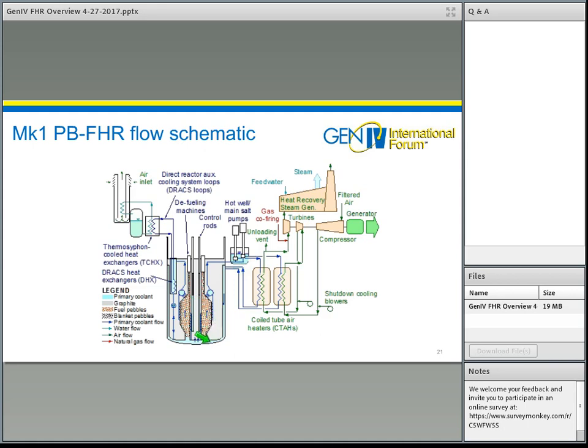The primary coolant is circulated up through the core and then goes out into a hot well. This has some similarities actually with the FFTF reactor design. And then the heated salt is circulated by pumps through 2 heat exchangers to heat air. The flow path for the air is to take air into a compressor, and with modern gas turbines like the Frame 7 turbines, pressure ratio is about 18, so the outlet temperature is in the range of about 420 degrees, which turns out to be a good temperature to go into the air heaters, where then heat transfer from salt to air raises the temperature of the air up to 670 degrees.